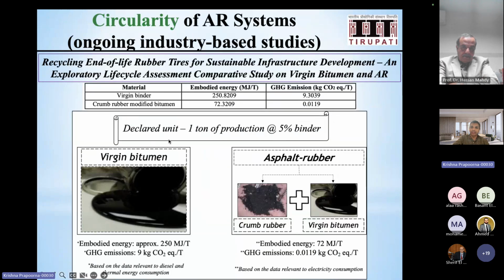And now again, the declared unit, I mentioned this already, the functional unit is 1 ton at 5% binder. I'm sure you have a binder content in your country as well. It could be 5 or 4.5, 5.5, something like that. So what we do here is calculate the embodied energy between the virgin binder and crumb rubber modified asphalt rubber. And you see here about 1/3 of the embodied energy gets reduced when you use asphalt rubber. And also GHG comes down by 250 times. So that is something really, really big, right? So what we have been able to clearly state with our studies, we have concluded, inferred, that recycling of rubber definitely yields very sustainable development of the infrastructure.